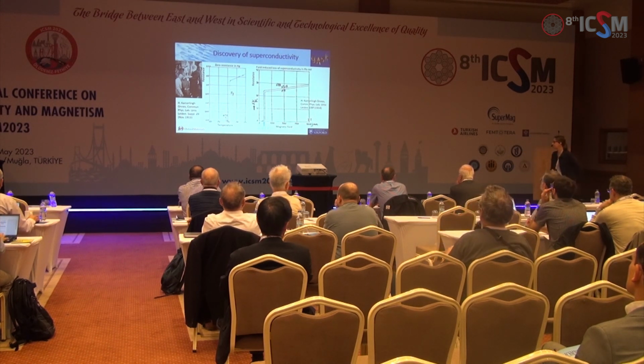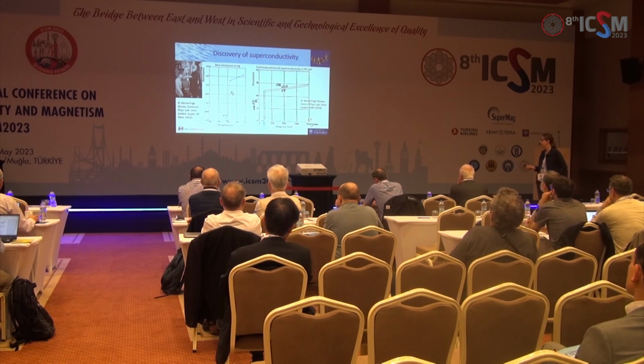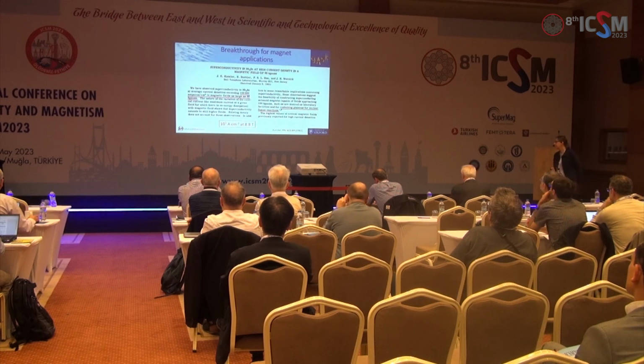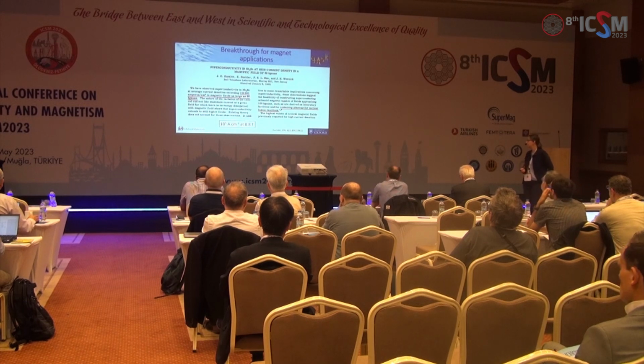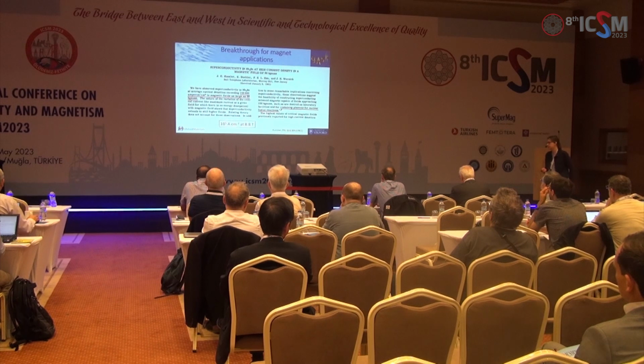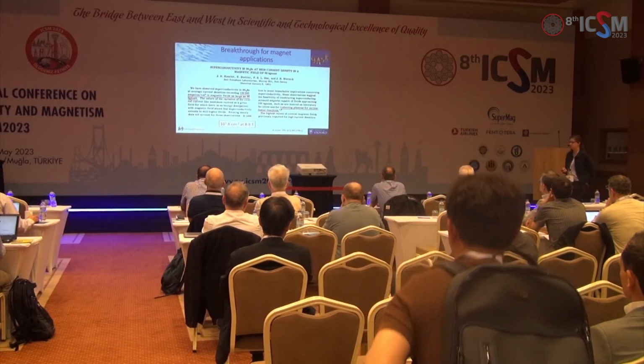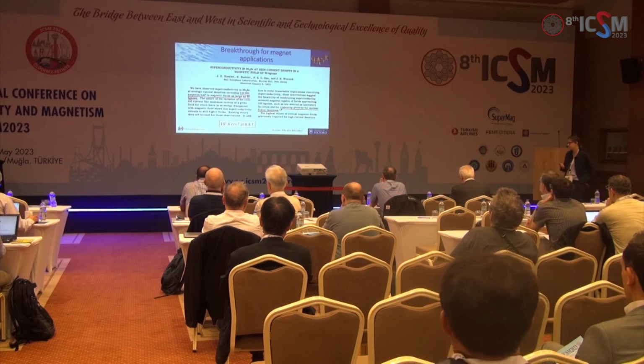So this was very disappointing for him, and it really wasn't until the 1960s when there was a breakthrough in this, and that was by Bell Labs, where they reported in niobium-3 tin, which had been discovered quite some years earlier, that they could engineer it to have critical currents of 10 to the 5 amps per centimetre squared at over 8 Tesla. So this was the first real high-field superconductor that we had. And in fact, in this very first publication, you'll see over here in the abstract, that they realised that this could be used for containing plasmas for nuclear fusion reactors, right back in the 1960s.